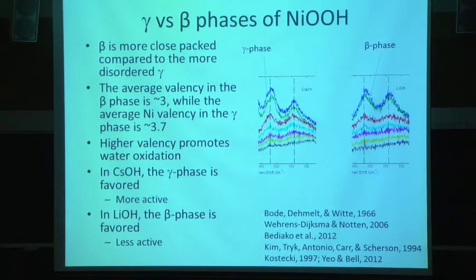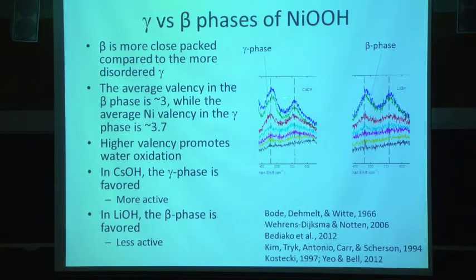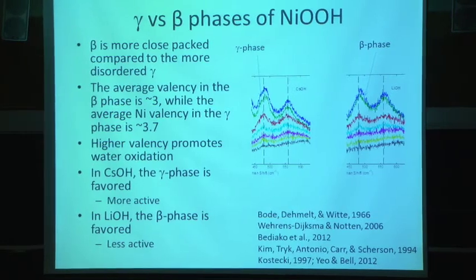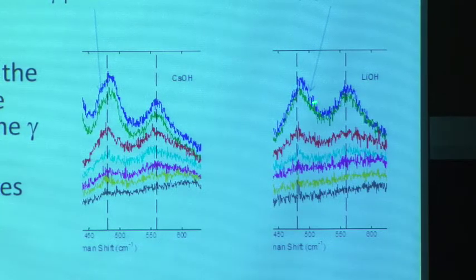So that's one piece, that you see already the formation of this at a lower potential in cesium than you do in lithium. But the other more subtle point is if you look at the distribution of points around the dashed lines. So over here you have the majority of points on this side. These are stiffer bonds that are associated with shorter nickel-oxygen bond lengths. That is much more like the beta phase of nickel oxyhydroxide. Over here you have more on the left side that's associated with longer bonds that are softer, right? So this is more like the gamma phase.